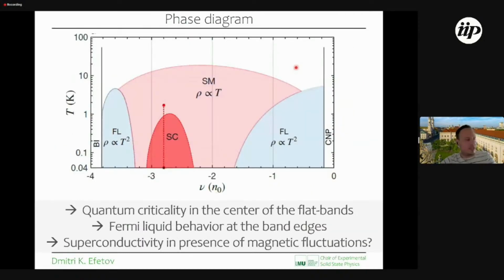And really, the last thing I want to say here is to summarize. The phase diagram which we obtained is the following. If you look at the phase diagram as a function of temperature and density in one of the flat band regions that we have, what is striking is that we observe Fermi liquid behavior very close to the band edges, to the insulator band edge and close to charge neutrality. Those Fermi liquid states are described by a power law, T squared, in the resistance. Those states are understood as Fermi liquids where, close to the band edge, the density of the metal becomes really low, interactions become a little bit weaker, and the Fermi liquid establishes itself.